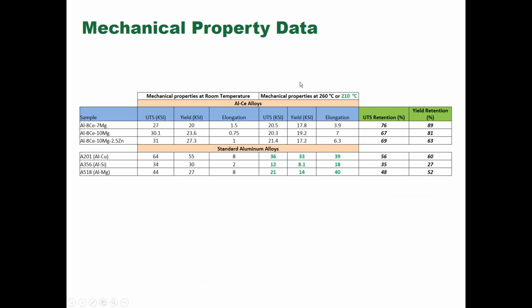So here's some mechanical property data. We've been working a lot with the cerium magnesium system, and in the case of 8 cerium 7 magnesium, you see some tensile, yield and elongation. And then in the case of the aluminum-cerium alloys, this is mechanical properties done at 260 degrees C or 500 degrees Fahrenheit. So at 500 degrees Fahrenheit, we're retaining over 20 KSI tensile in a whole series of alloys here.